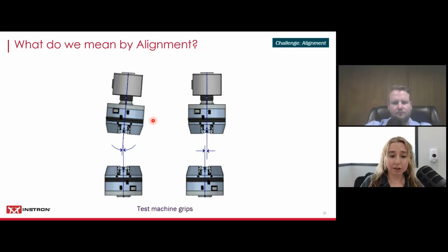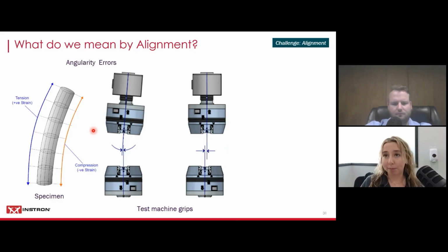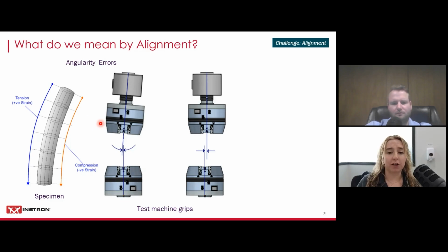But on the left, we are not coaxially aligned. So this is causing an angularity error. Our top grip is not parallel to the bottom grip. And what happens is that our specimen is actually bending, and we're creating a positive strain on one side of the specimen and a negative strain on the other side of the specimen. And I'm going to typically refer to this kind of bending as a bending moment.